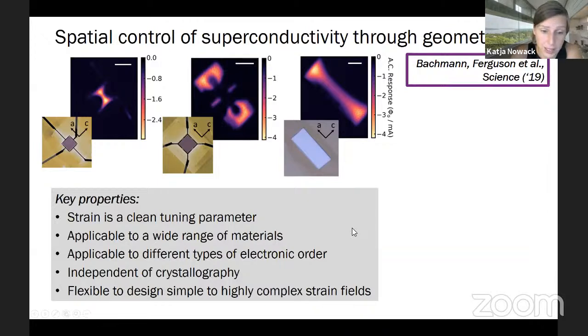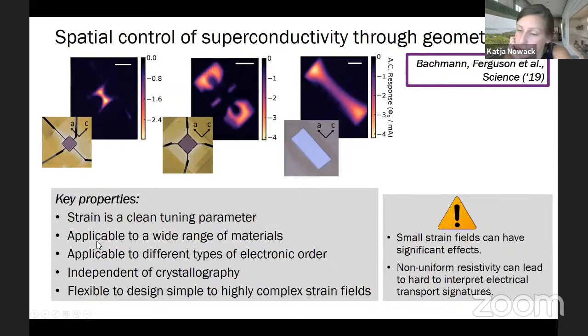You could also think about applying this to different types of electronic order, for instance, magnetic order. The focused ion beam devices, I didn't point that out, were all oriented along specific crystal axes, always the A-axis and the C-axis. But you can cut the kind of lamellas that we work with at any angle, so you can also play with crystal orientation. This approach gives you a lot of flexibility to design fairly simple to highly complex strain fields. This was also a cautionary tale.